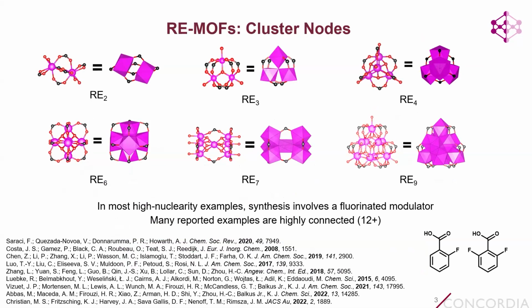And so when it comes to making these rare earth cluster-based MOFs, these are just some examples of the rare earth clusters that we have access to and that we can use as building blocks to make these MOFs. You can see the diversity in these clusters in terms of the nuclearity, their connectivity, and their geometry. And this type of diversity is really exciting as a MOF chemist, but it also poses a very significant synthetic challenge because it can be quite difficult to control the generation of specific clusters in situ during the solvothermal synthesis of MOFs, particularly the high nuclearity hexa, hepta, and nonanuclear clusters shown here.